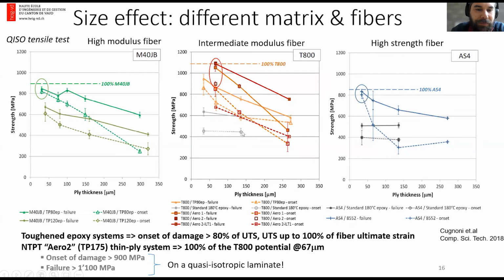I would imagine that it could be the same in some thermoplastics because of the weak fiber matrix interface. However, if you have a very good fiber matrix adhesion, then you'll be dominated by matrix plasticity, and you will restore the behavior like the one we observed. So that's my guess, but I've never tested it.